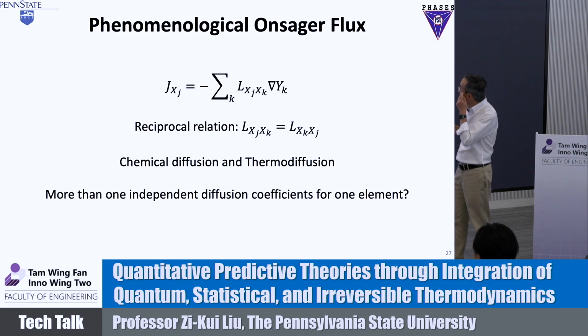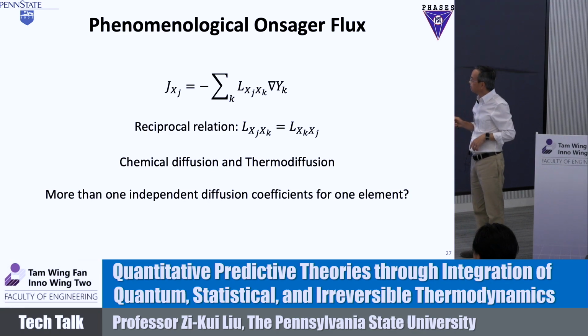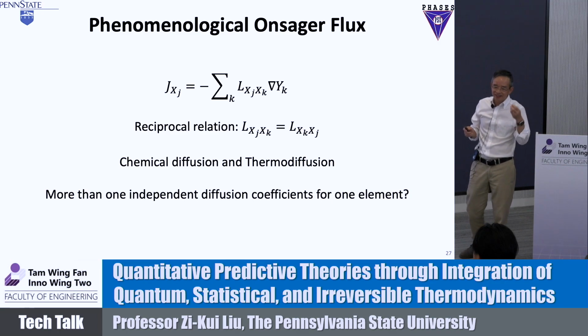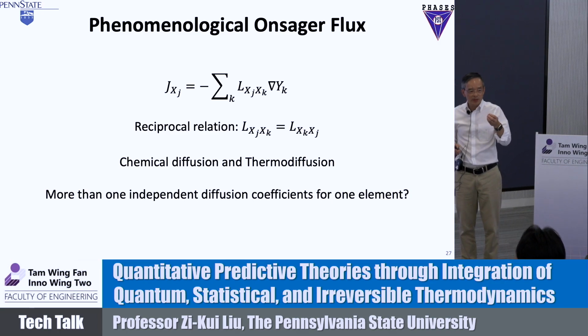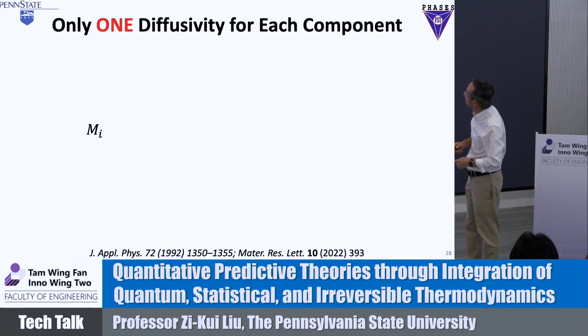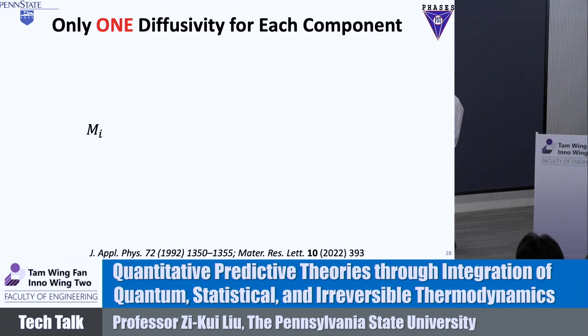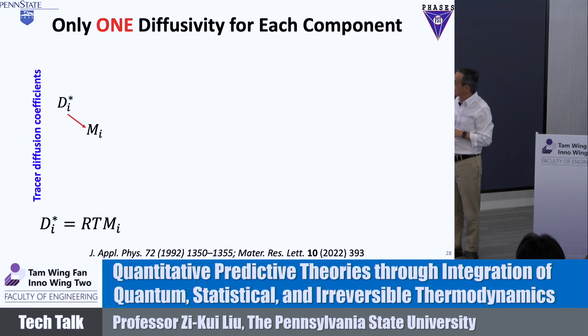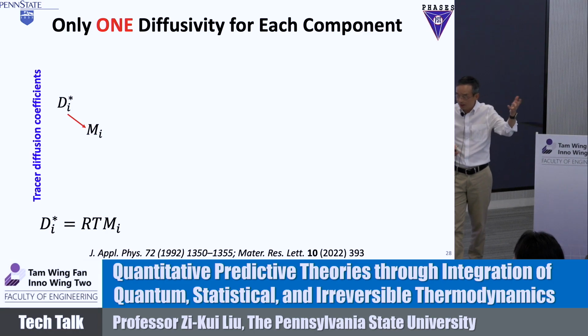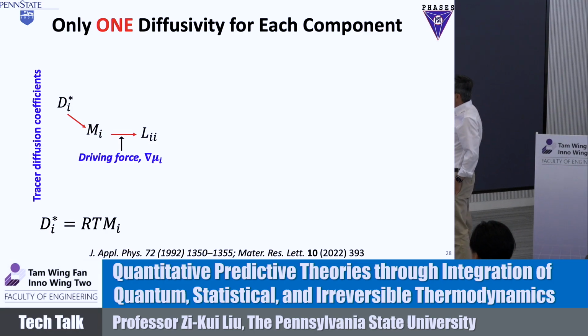This was in 2014 and 2015. I didn't have a project, so I buried that problem in my brain. That professor always invites me to his diffusion meeting, so every time I go to present a little bit. Then I use this one argument: there's only one diffusivity for each component. It's the mobility of the atom. The mobility of the atom can connect to the tracer diffusivity with the Einstein equation. However, in the experiment, we measure so many diffusivities, just like the Onsager equation. What it means is that mobility gets a driving force, and gets a parameter in the flux equation.